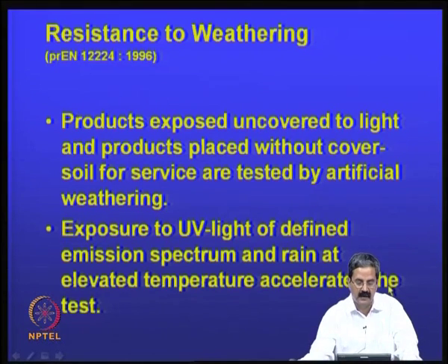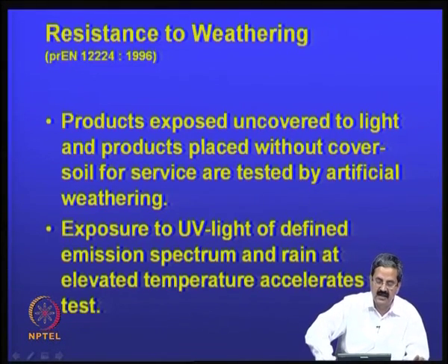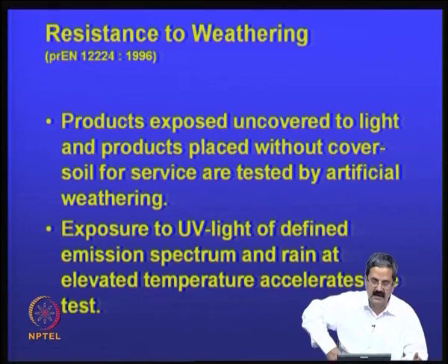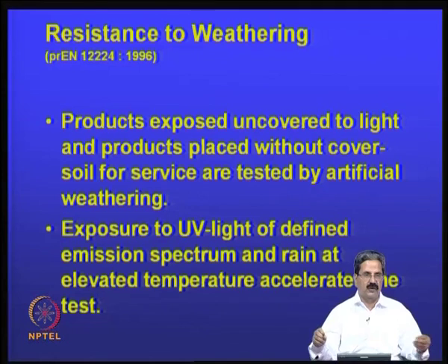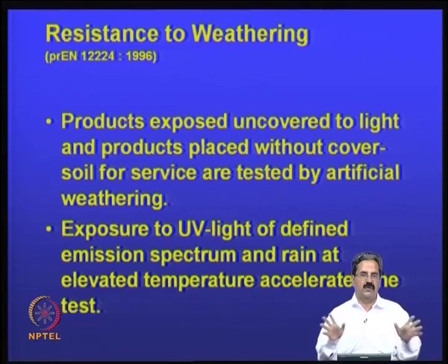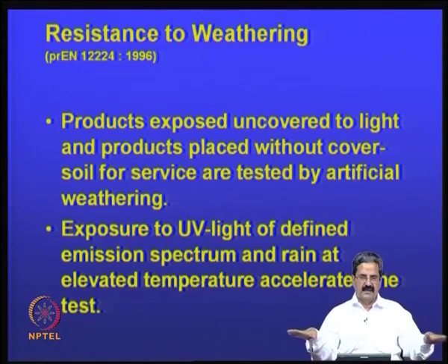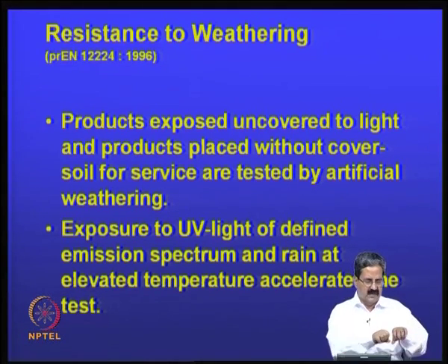Resistance to weathering, what is that? It is essentially that products exposed to uncovered light, if you do not cover them properly, are exposed to ultraviolet rays. I have seen that if you take a geosynthetic material and leave it outside, initially it is nice, but after that, because of the ultraviolet exposure, the sunlight exposure, it gets very stiff, and after that you can even break it with your hand.